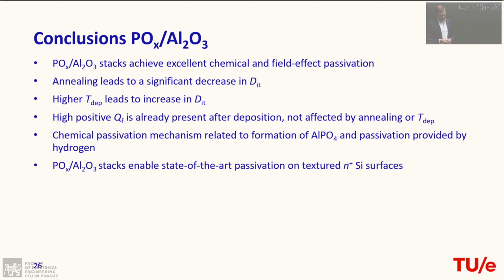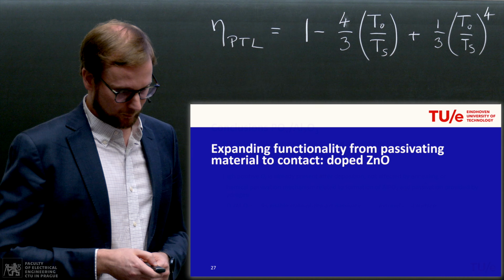So, conclusions for this topic at least. We have seen that this phosphorus oxide aluminum oxide stack can achieve excellent chemical passivation and also field-effect passivation. Annealing improves DIT. Also, deposition temperature can be used to lower the DIT. Your high QF value is already present after your deposition, so you don't need to worry too much about optimizing this. And chemical passivation is understood to be linked to the formation of AlPO4 and also hydrogen, which is released. And then it is indeed possible to passivate typical N+ silicon surfaces that appear in conventional PERC cells. So that is part one of my material overview.